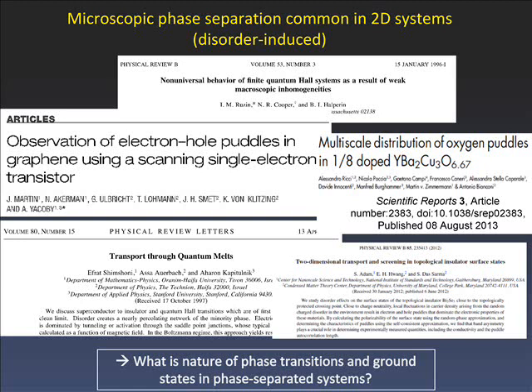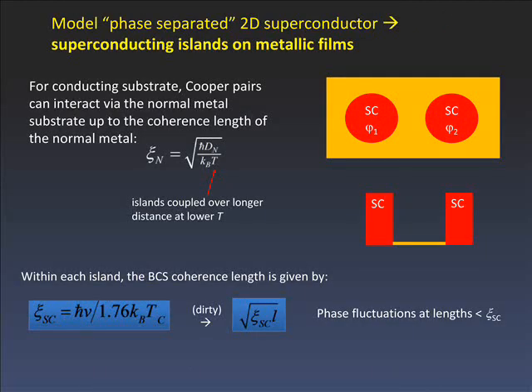This all motivated us to try to create a model of a phase-separated interacting system and see what sort of physics emerged and how we can compare it to other systems. Our very simple model — a phase-separated system — is a system of superconducting islands on a metallic substrate. The superconducting islands interact via the metallic substrate: if you have phase coherence between them, you can pass pairs between them; if you don't have phase coherence, you don't get a supercurrent across the system.